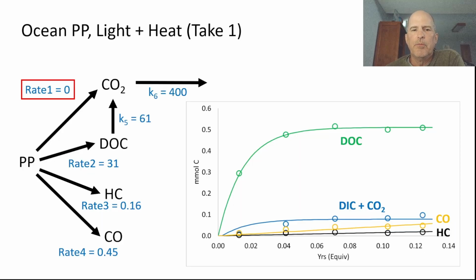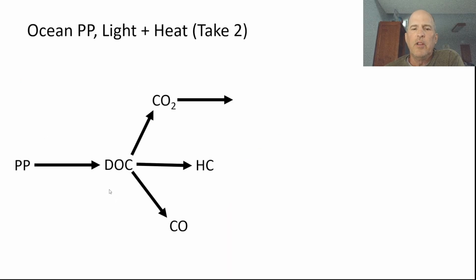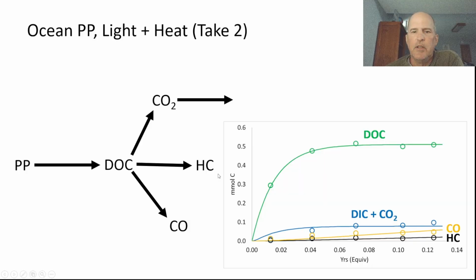And I thought, well, it's probably relatively unlikely that any of these small molecules are going to come directly from the polypropylene. Probably they all come from the dissolved organic carbon. And so I moved to this model where you just have one rate going from the polypropylene to the dissolved organic carbon, and then that splits off to these three different gaseous products, and then I still have CO2 escaping the vessel. And I fit that, and the fit is just as good.